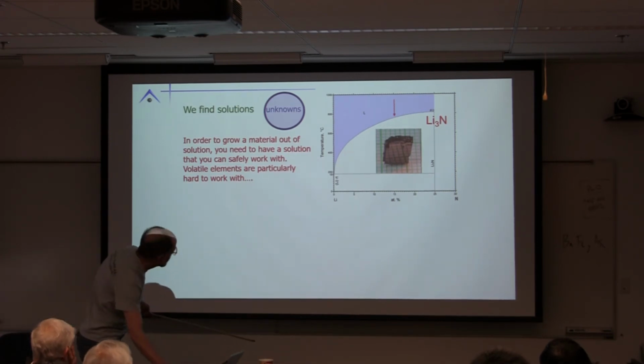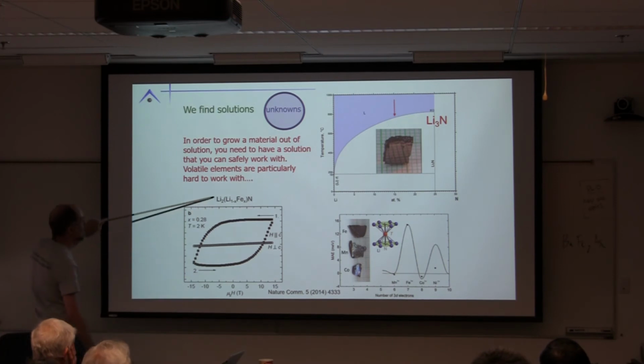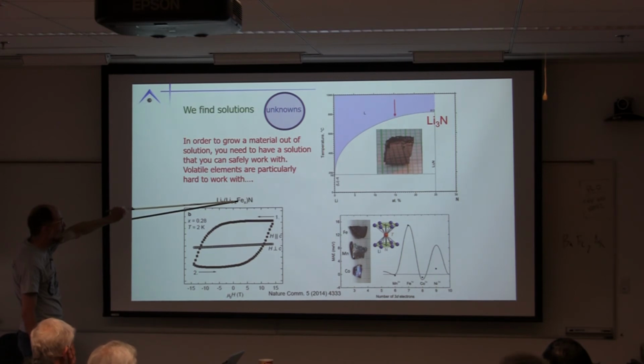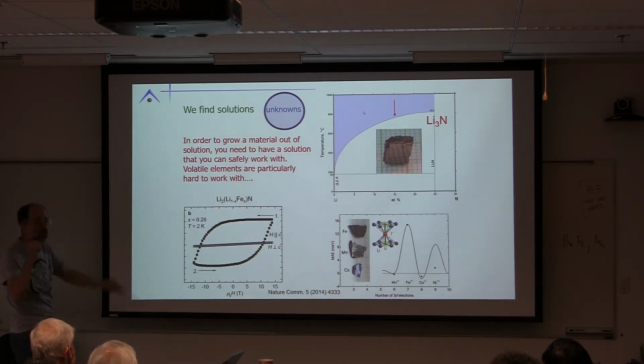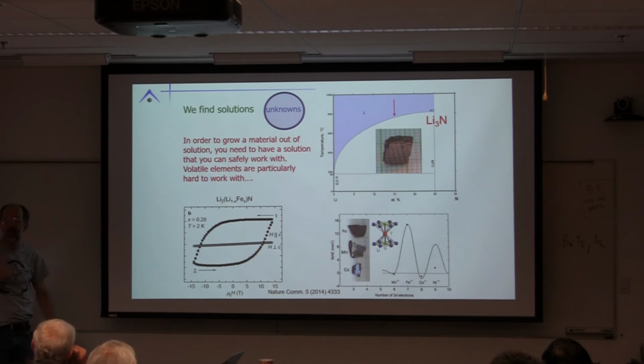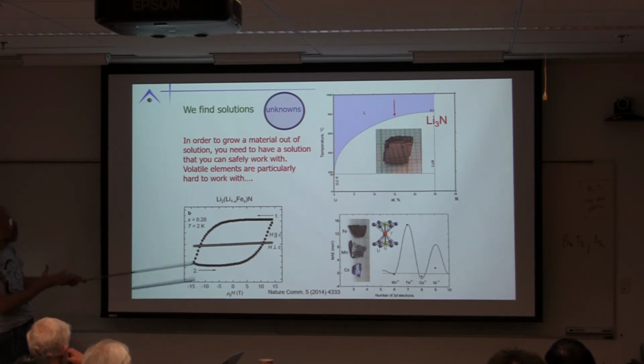Okay? Now, one of the first things we did then is appreciate that lithium 3 nitrogen has 2 lithium sites, and on one of them we can substitute in transition metals, and when you substitute in iron, you can have local moment physics that has anisotropy larger than any rare earth I'm aware of. Okay? Now this is a weird exception to the Jahn-Teller rule, because it's a one-dimensional environment. Okay? But it was really neat stuff, and we've continued to explore other solutions that we can make with nitrogen and try to grow nitrides out of solution. Okay? So that's sort of fun.